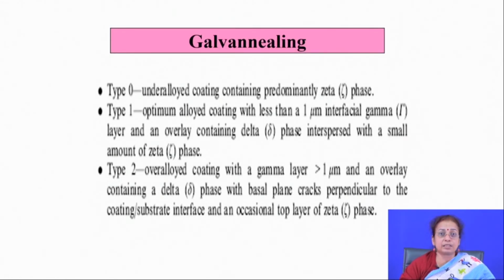So, as I mentioned, these are the 3 important ways by which you do the galvanizing process, and each and every bath has its own advantages and disadvantages, and also there is a lot of cost associated with aluminum addition. So, if you add aluminum to a large extent, the temperature of operation goes high, and also for maintenance of the fluidity of the bath you have to take proper precaution. These problems are always there, but again you get some advantages which are not possible to achieve by the normal single-step galvanizing process.